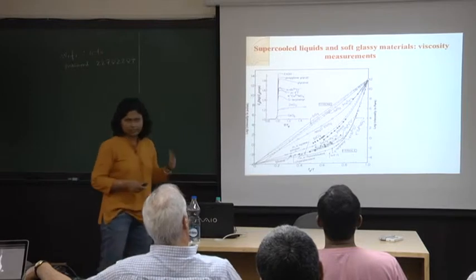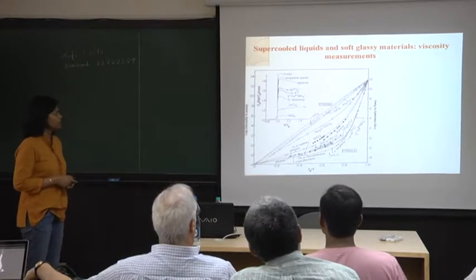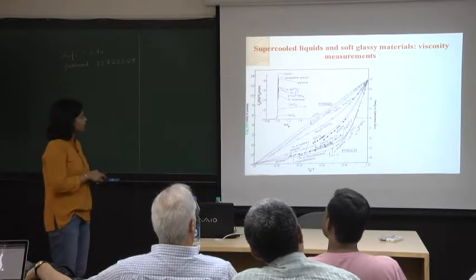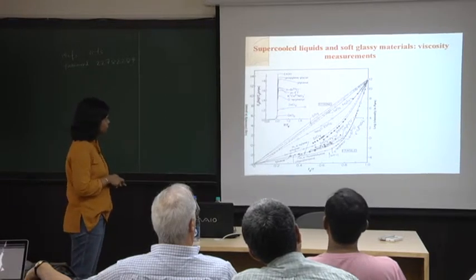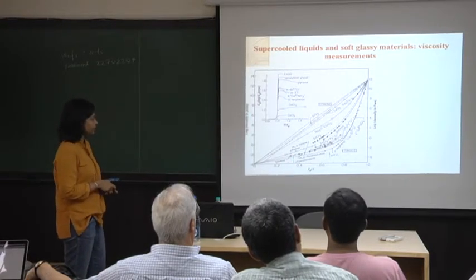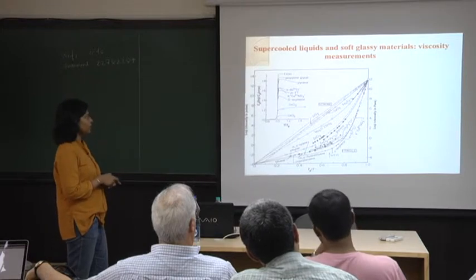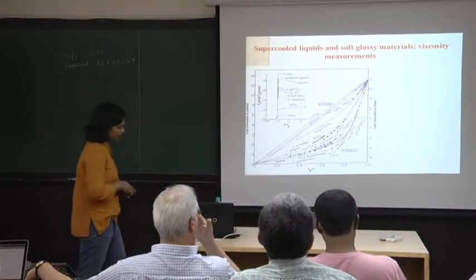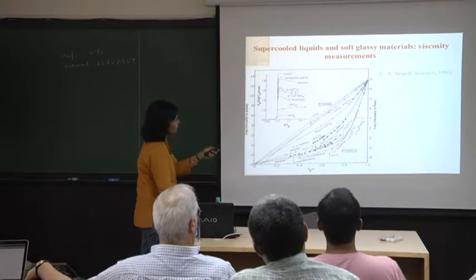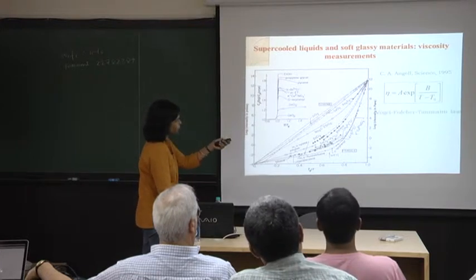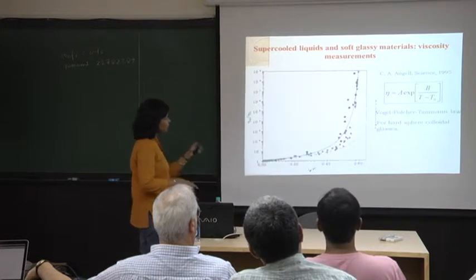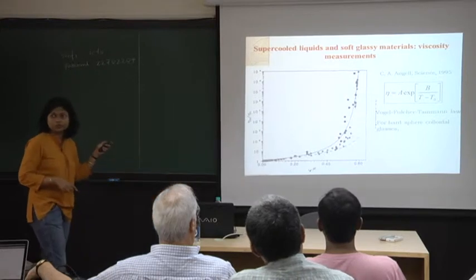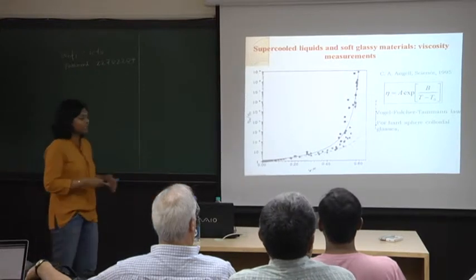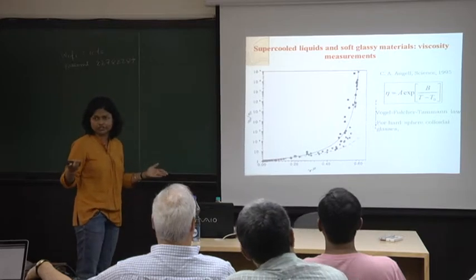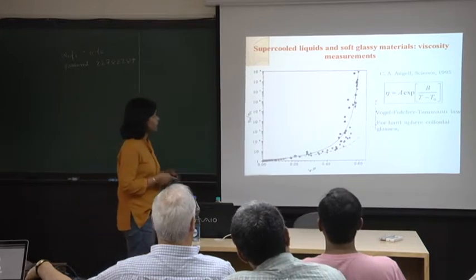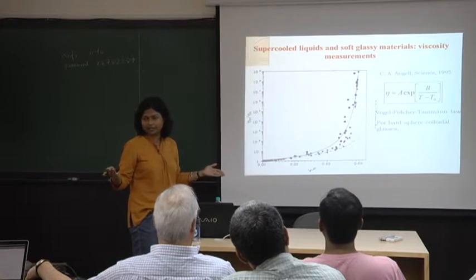Okay, viscosity measurements. We do a lot of rheology work. So we'll have to come back to this Angell plot, which was basically the plot of the viscosities versus the inverse of the temperature for strong as well as fragile liquids. And I've already told you about the Vogel-Fulcher-Tammann law. Now for glasses, you see that viscosities do evolve in a very similar manner, except that the dynamic range of the viscosity is not quite as large.